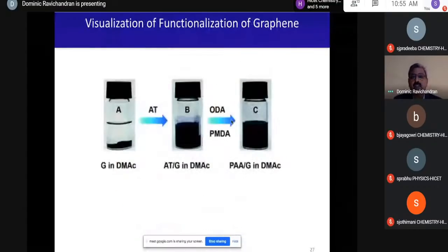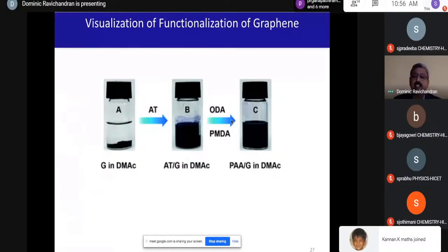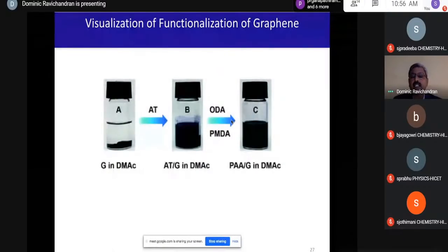Here you can visualize how the functionalization is going to disperse the graphene into the medium. The first one, that is A, is the graphene in a solvent of dimethyl acetate. When you add graphene to dimethyl acetate, it settles down and it is not getting dispersed. But when it is attached with aniline trimer, you see that the graphene is dispersed. The same way, when you have a PAA graphene composite in a solvent like dimethyl acetate, it gets dispersed. And these properties, that is the solubilizing property and also the attachment of these organic moieties, help in modifying these graphenes and tailor-make the graphene to our need.